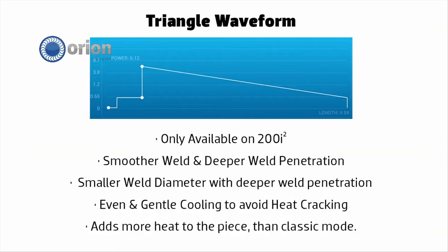You get a smoother weld and deeper weld penetration compared to classic when using this waveform. You have a smaller weld diameter, but with deeper weld penetration. You can set the settings to where you can really hit it with the right amount of power to have a smaller weld diameter and deeper weld penetration than you could with the classic. You get even and gentle cooling to avoid heat cracking. So you're getting a deeper penetration, and it's really important to have that equal, even and gentle cooling, to make a stronger weld so that there's no chance of cracking.